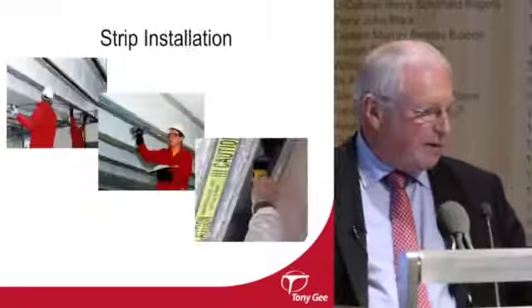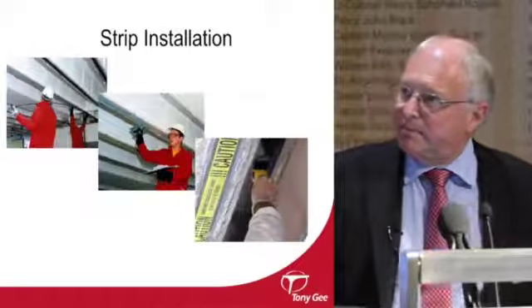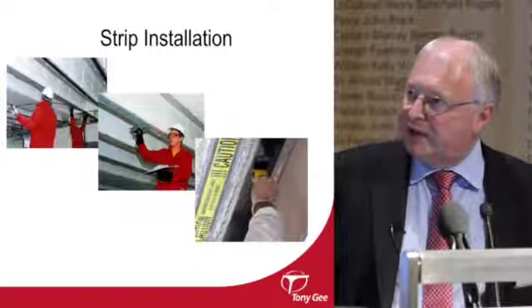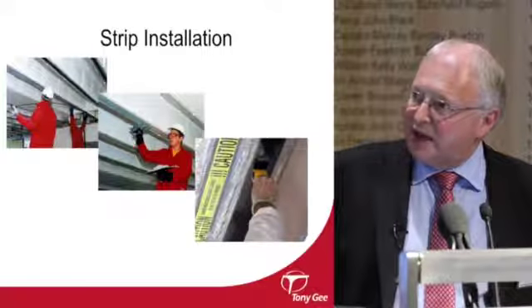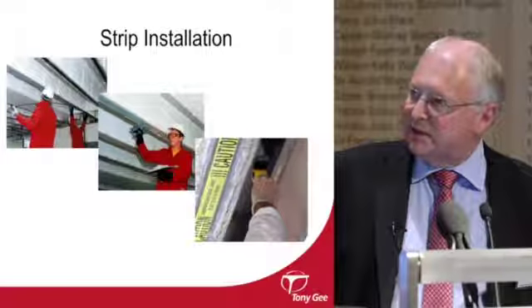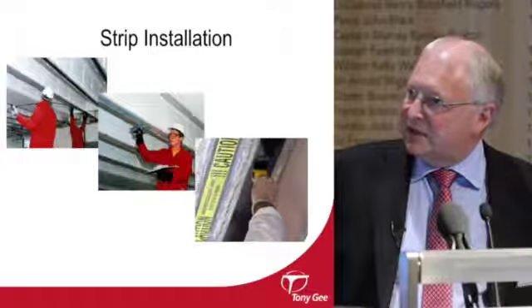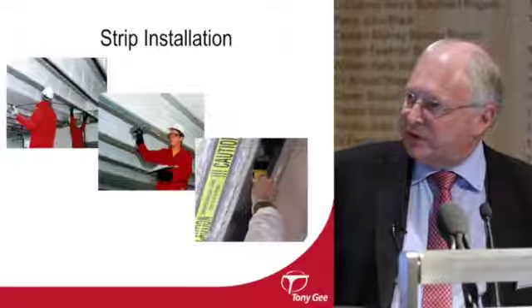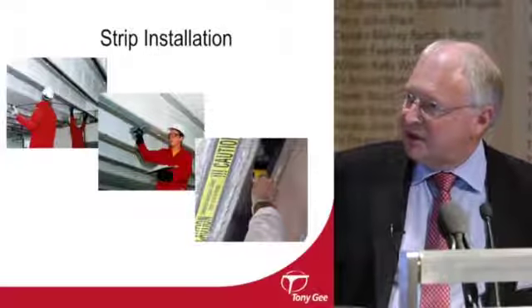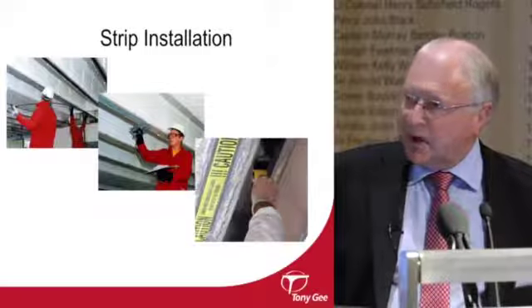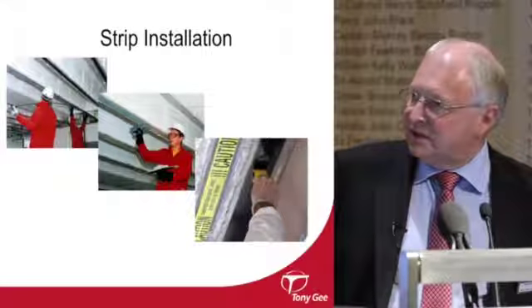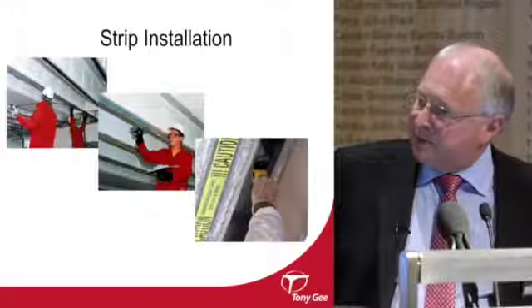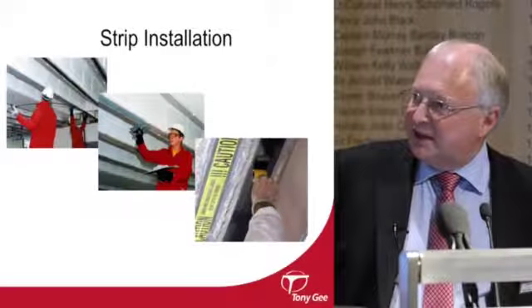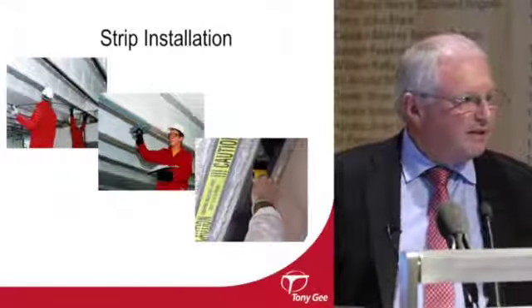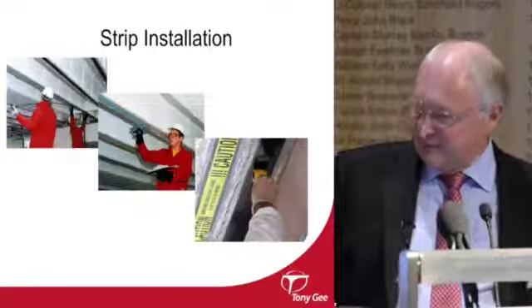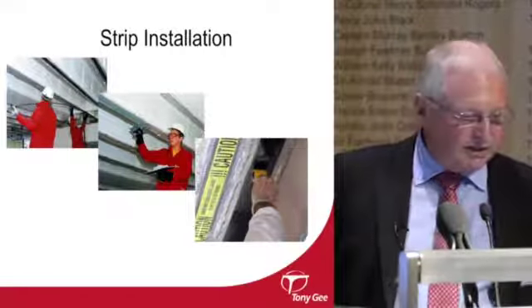This is the strips being installed. The concrete's clearly been prepared, just like for steel plate bonding. An adhesive layer, typically about 2 millimetres thick, is applied onto the concrete, and then the strips are offered up as they're doing there, and a roller rolled down the middle. You have to be careful not to over-roll it and draw air back into the joint. Some people actually put a warning sign on the strip as well, so that people don't come along and start drilling through it as future trades follow, particularly in the building trade.